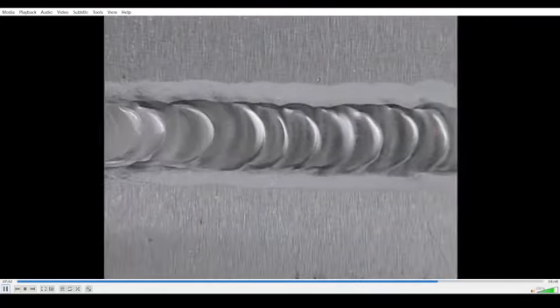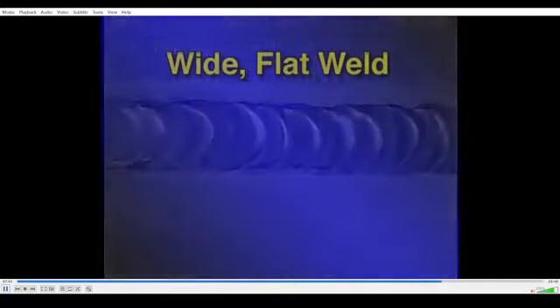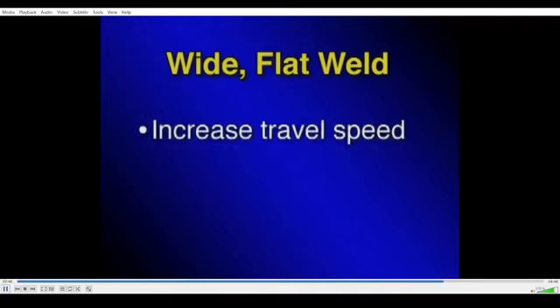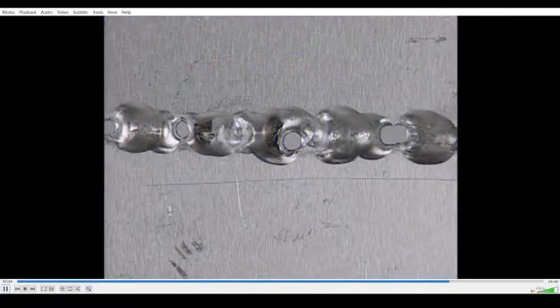A wide flat weld with excessive undercut indicates too much amperage. You can control this problem by increasing your travel speed and reducing the current as you progress along the joint to compensate for heat buildup. Remember that heat travels quickly in aluminum, so you have to pay close attention to amperage in order to minimize loss of strength and to prevent burn-through, especially on thinner material and on open root welds.